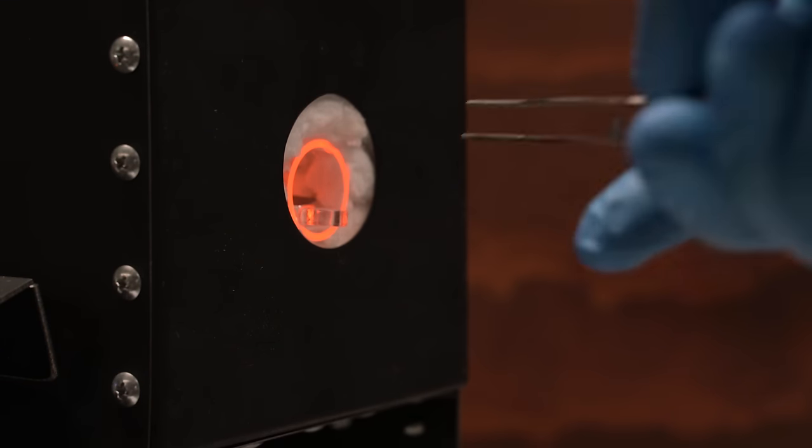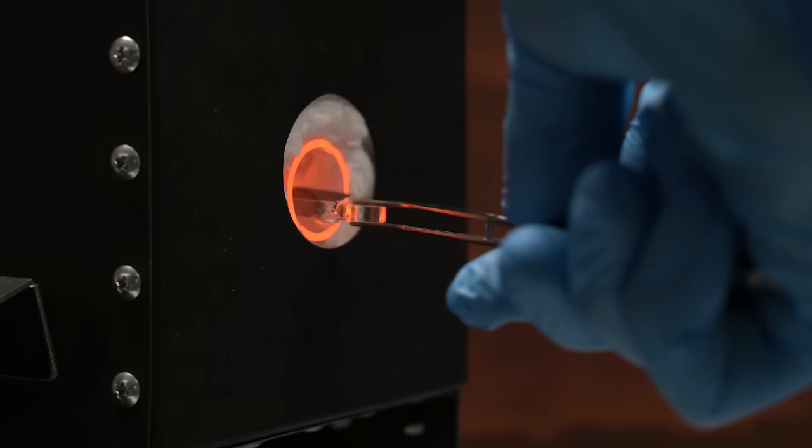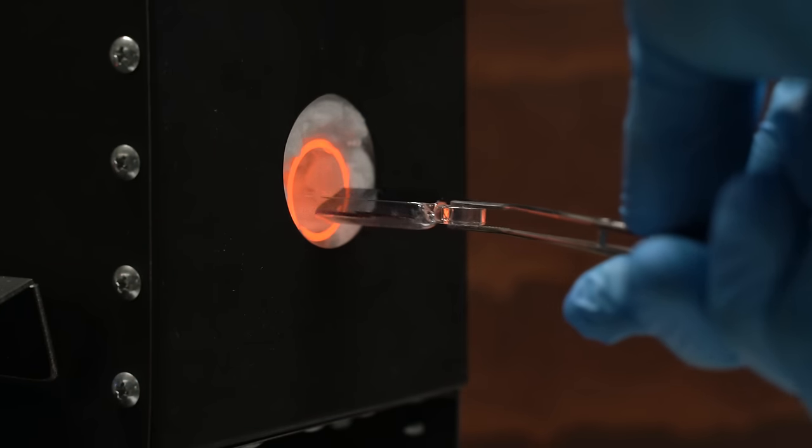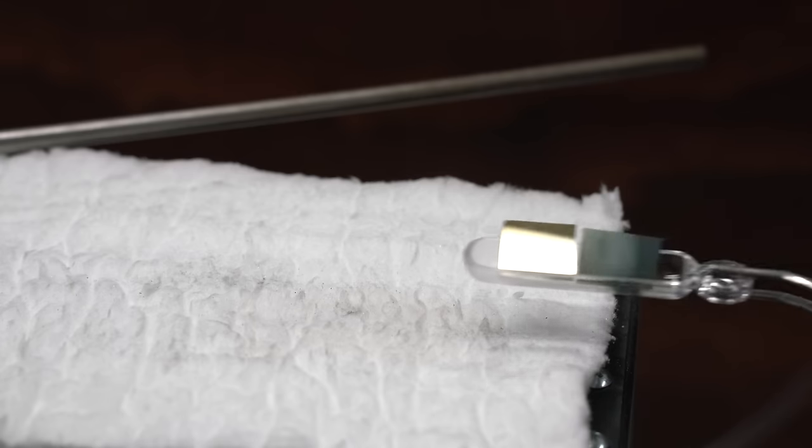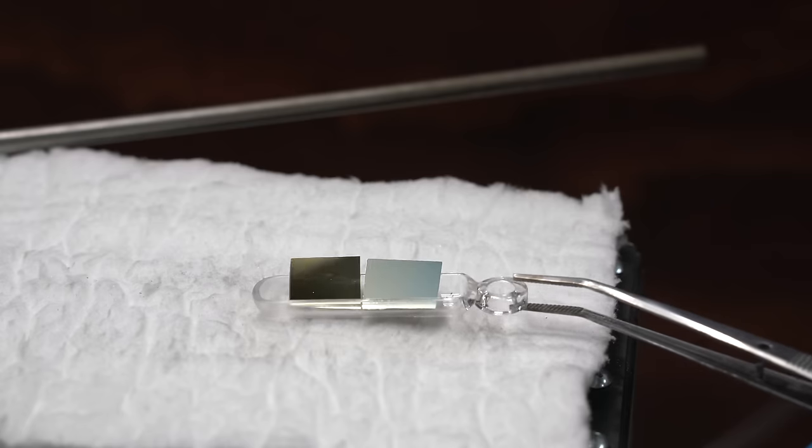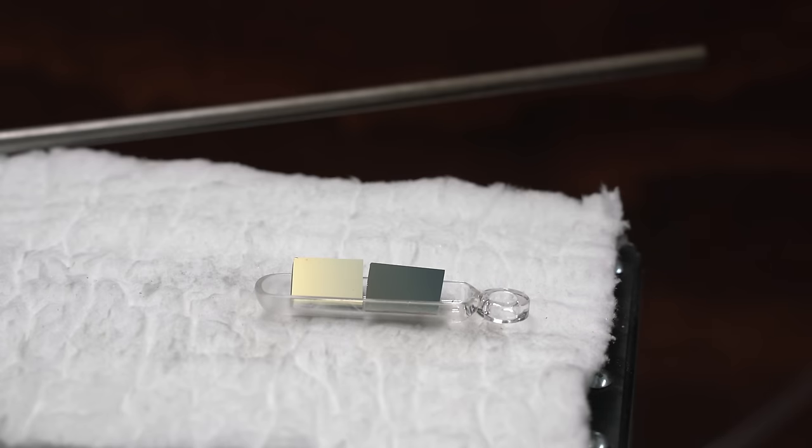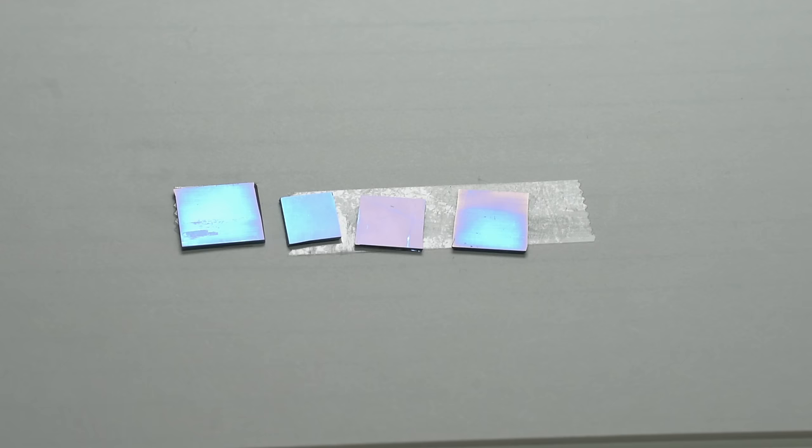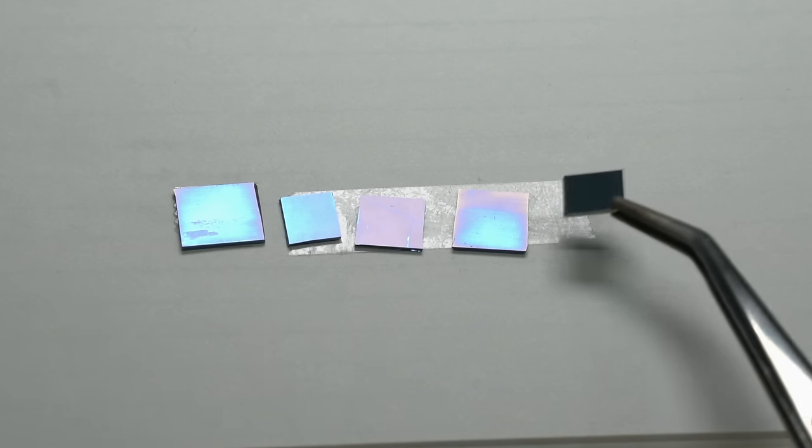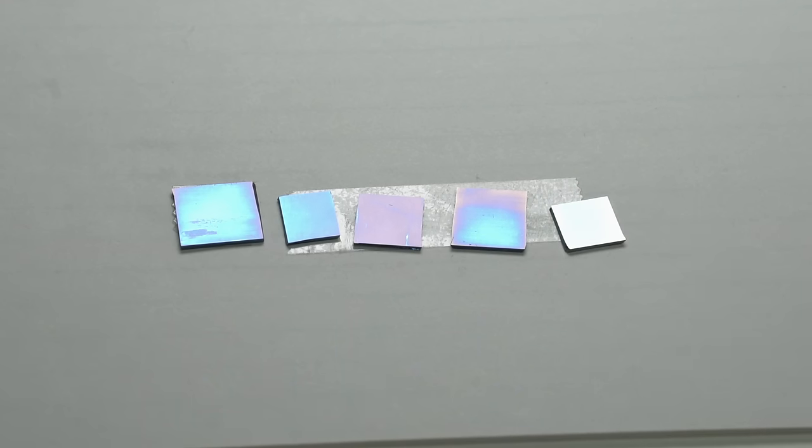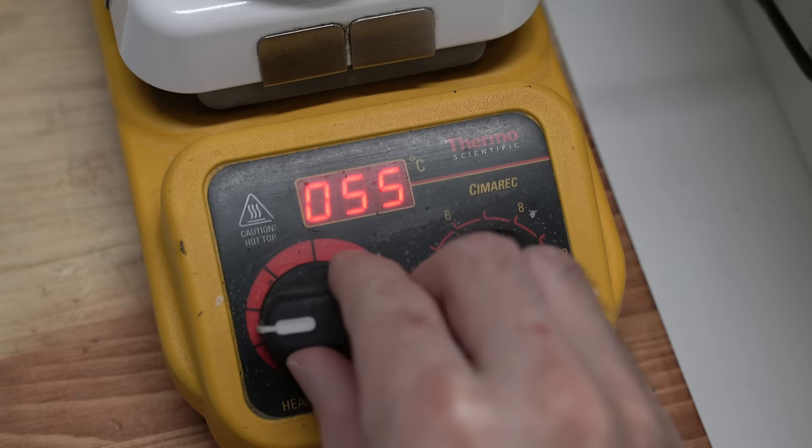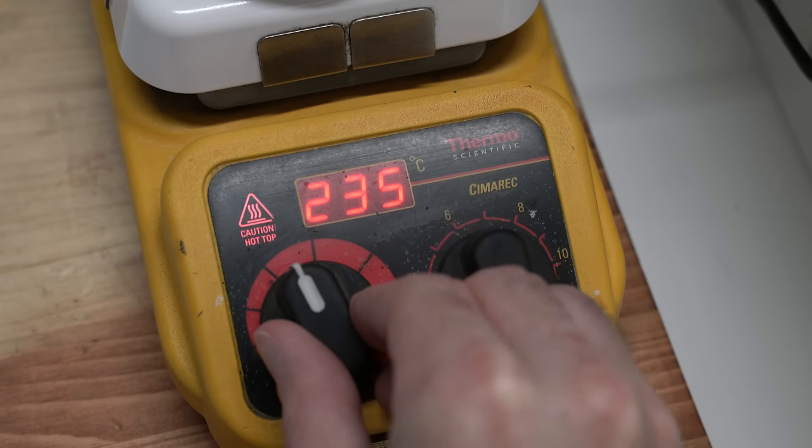I did have to track down one more issue with the furnace, and this one took me a while to notice. I had already accounted for the temperature gradient and was making sure all of my chips were placed directly in the center, but I was still seeing problems. Most of my oxide layers were coming in below the expected values, and worse still, the exact amount of that difference was inconsistent. The variables in the formula for wet oxide growth are temperature and time, so I was a little confused what was going on. Well, as it turns out, it was because the steam generator wasn't operating properly.